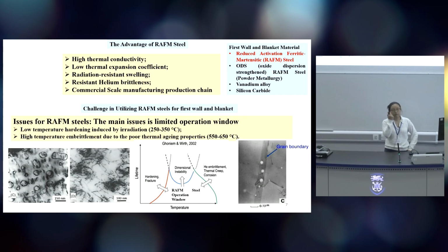So currently, we have a few materials we can select for the first wall and the blanket. Comparing with the other materials I list here, the reduced activation ferritic martensitic steels have high thermal conductivity, a low thermal expansion coefficient, good radiation resistance to swelling and helium embrittlement, and, just as important, they have a commercial scale manufacturing production chain to supply the production in the future, which makes the RAFM steel an ideal candidate for the first wall and the blanket material. But we still have a challenge in selecting RAFM steel because they have a narrow operation window. This is due to the low temperature hardening induced by the irradiation and the high temperature embrittlement.